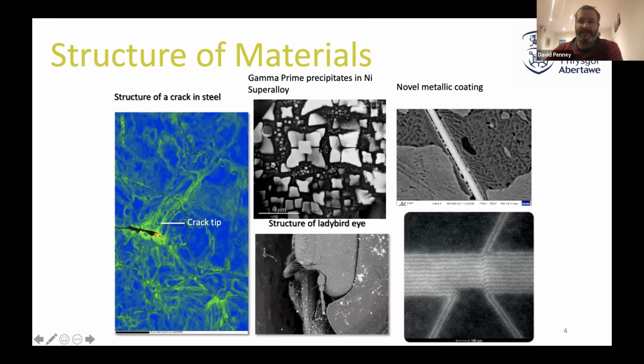Here's an image in the center of a nickel superalloy, which we've added these precipitates or grown these precipitates, with these square things here. And what they do is when the materials are high temperature under stress, so if you think about a jet engine, high temperature, 1,000 odd degrees, rotating so fast, it's the equivalent of having 2 double-decker buses hanging off the end of the turbine blades. So it's a hell of a lot of stress. These precipitates help to keep the material in one piece.